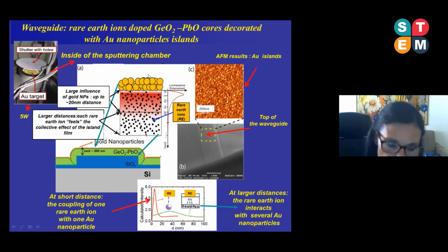I would like to highlight two important mechanisms that influence the luminescence of the rare earth ions that are distributed all over the core and represented by black points in my figure. We have the short and long range enhancement mechanisms. At shorter distance, we have a large influence of gold nanoparticles, up to 20 nanometers distance from the island. So in this case, we assume the coupling of one rare earth ion with one gold nanoparticle. However, at larger distance, each rare earth ion feels the collective effect of the island film. So this is represented here.